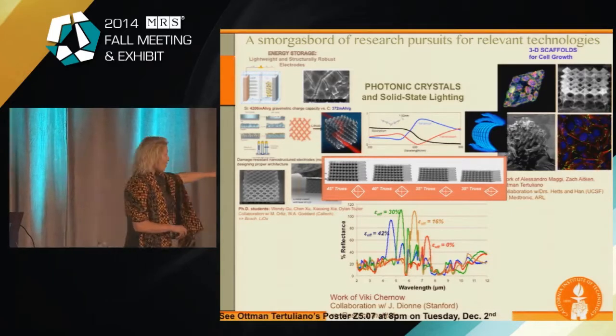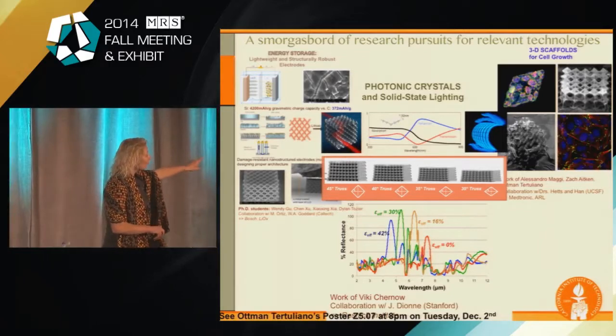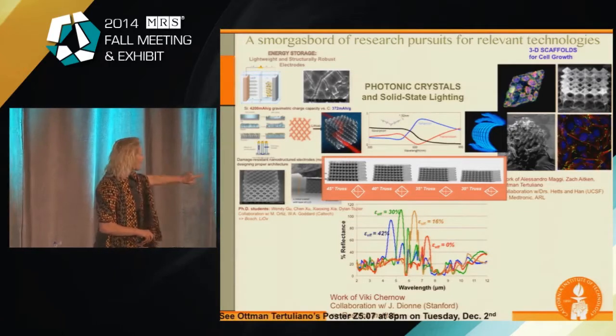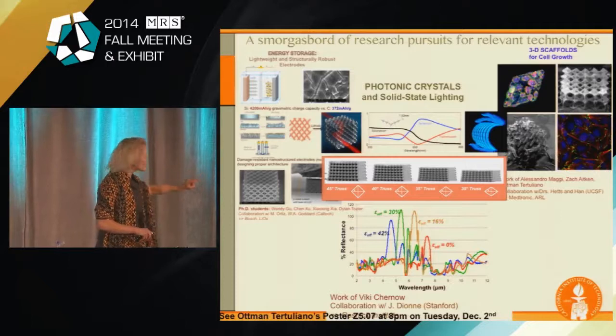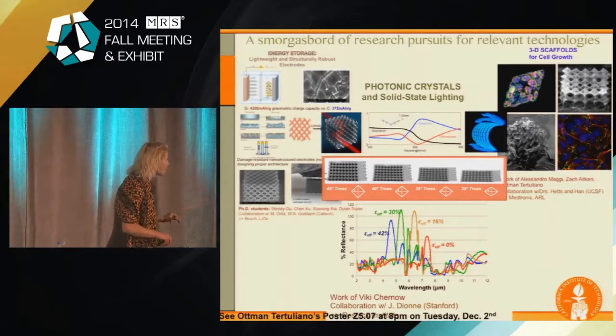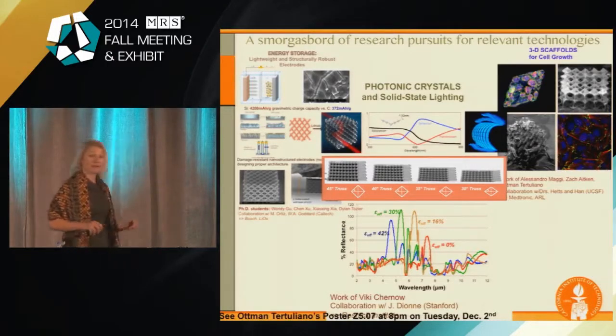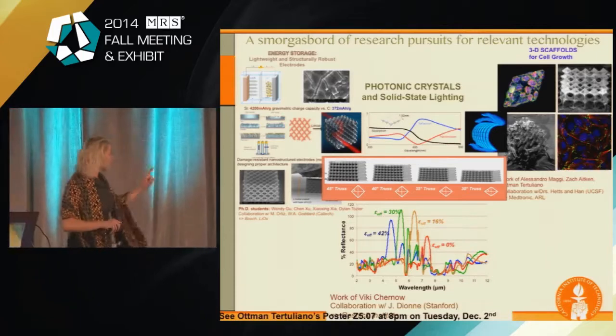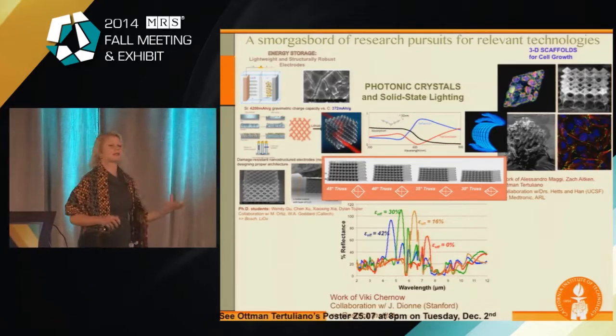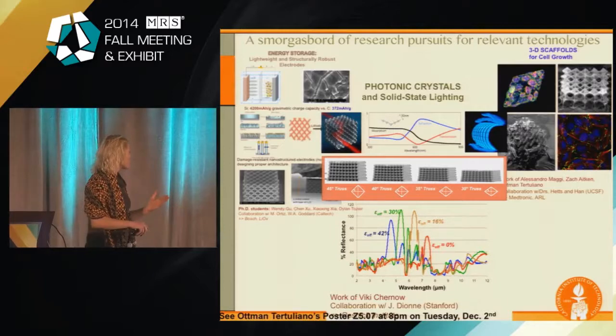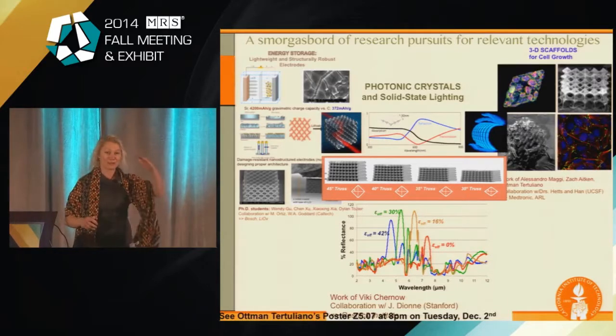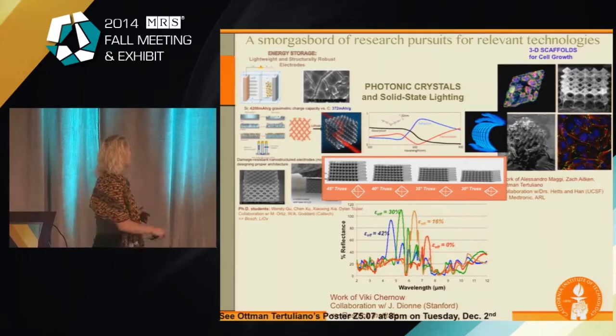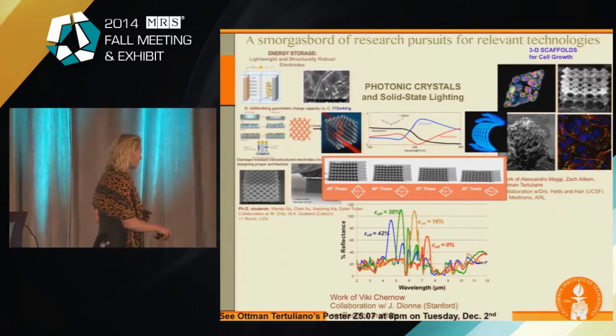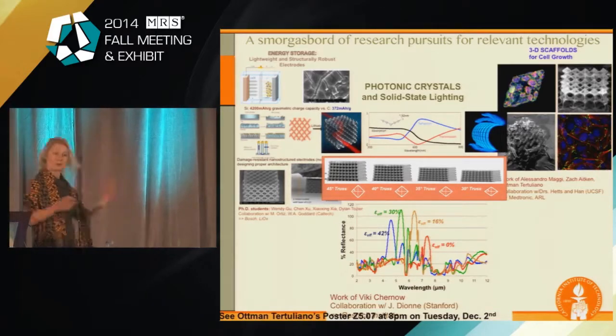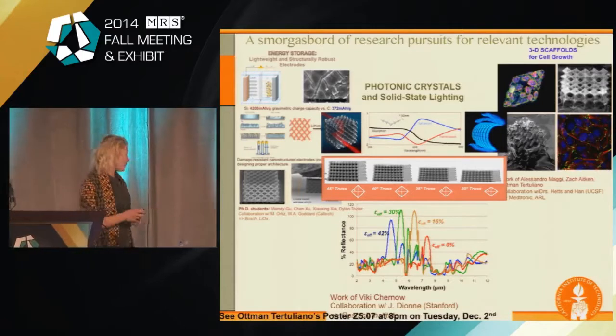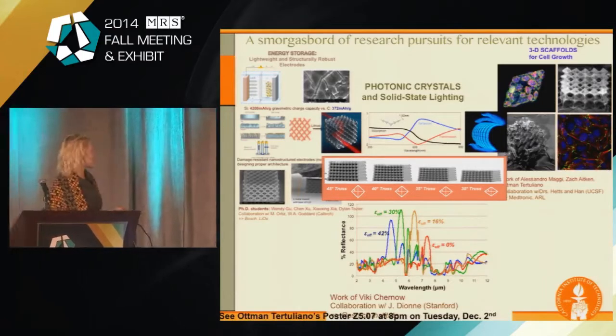and now what she's showing even more is that as you compress these nanolattices, the photonic band gap shifts. And this is in the near IR range, but you can see how tremendous the shift is. It's on the order of microns, about 5 microns. So these can be made into, for example, ultra-precise optical switches, right? It would be great if we could push it into the visible so you could see it change light with compression rates. It goes from blue to green. So this is also a collaboration with Professor Jennifer Dionne, who won this award last year from Stanford University. So this is pretty exciting.